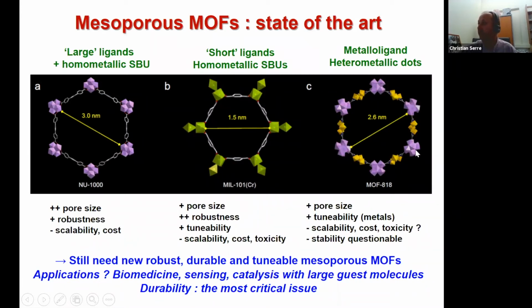And then more recently, some people reported the use of a combination of building units. So here, zirconium-6 and copper building units. And they could establish, here you see that on the left and the center, you have 6-member ring building units. Here you have 12 building units in the same ring. So it expands the size of the windows and therefore the porosity of the material. So this is quite interesting.